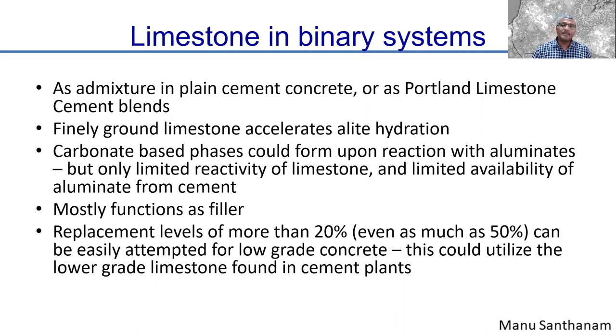So in reality, much of this limestone simply acts as a filler. It's a non-reactive material in most of the cases and simply sits there as a filler. But even that is actually a good performance because ultimately you're blocking the porosity. So when you start replacing with larger quantities, as much as 50%, you can still make good quality, low-grade concrete.